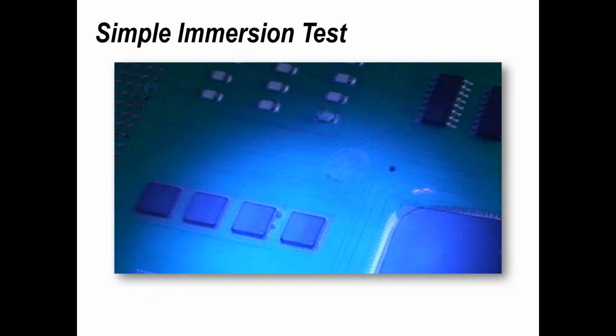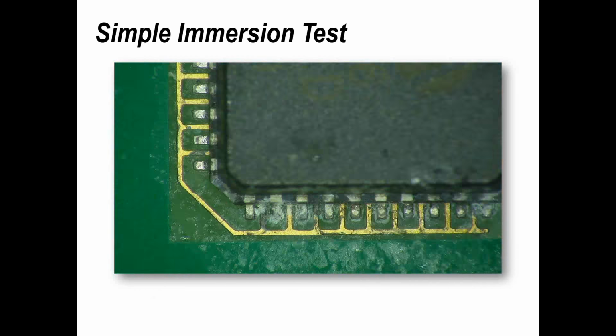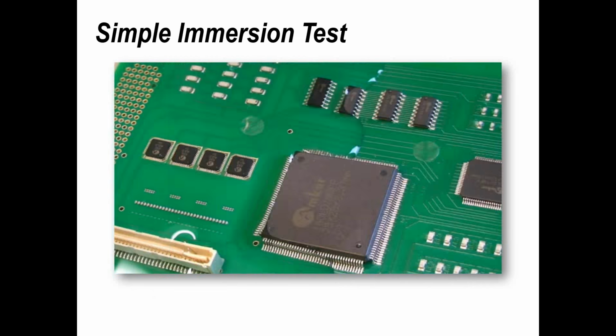And what you can actually see, obviously this one is conformally coated, and after testing, you can see the corrosion that I show in this particular photograph. The point here is that a very crude test, taking a board, if it's been conformally coated right, it will give a better level of protection, even on this rather difficult to pass test. But the company originally, when they were doing this, all they were trying to do is just look at the consistency of conformal coating, and it was quite crude but effective in actually seeing the actual results.